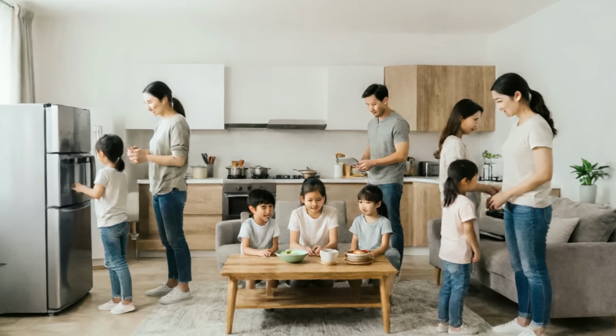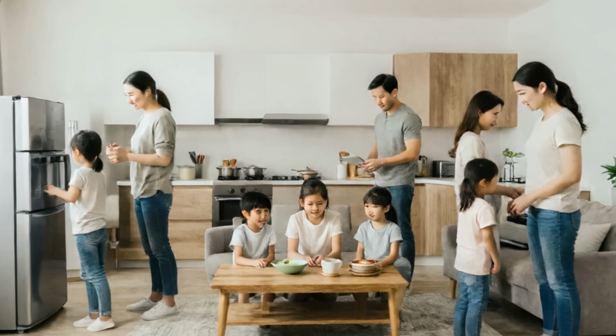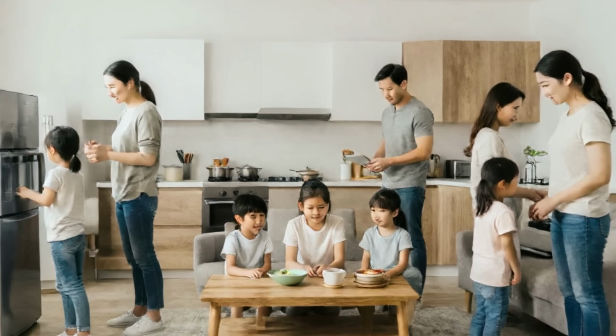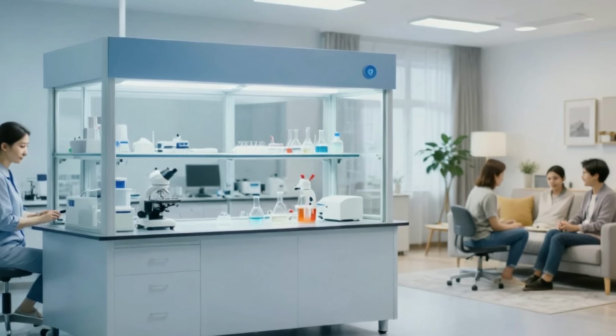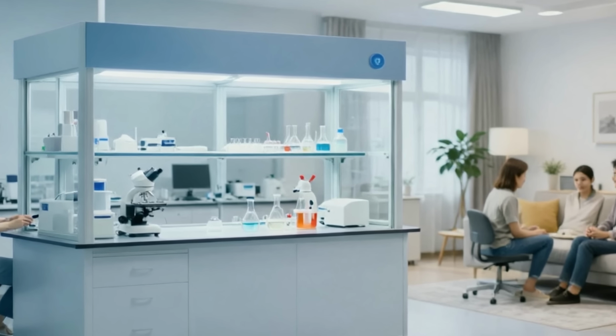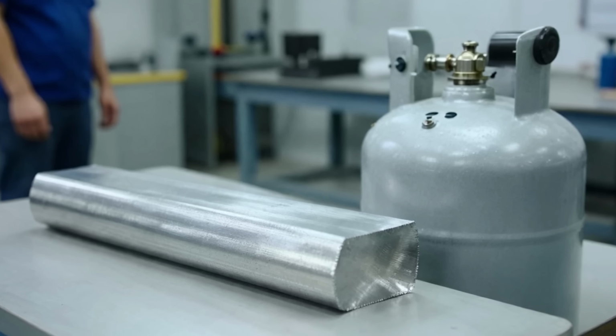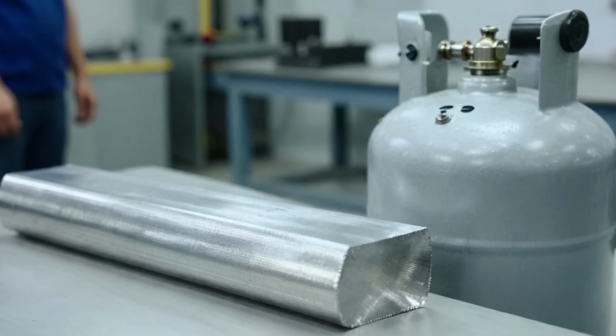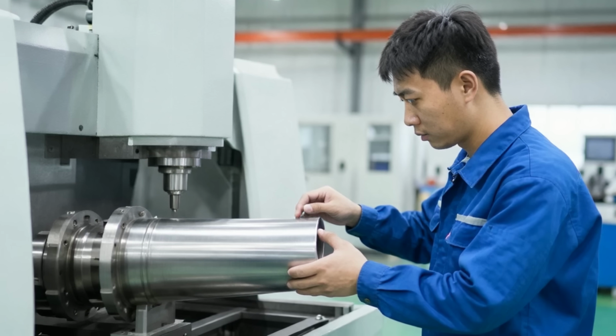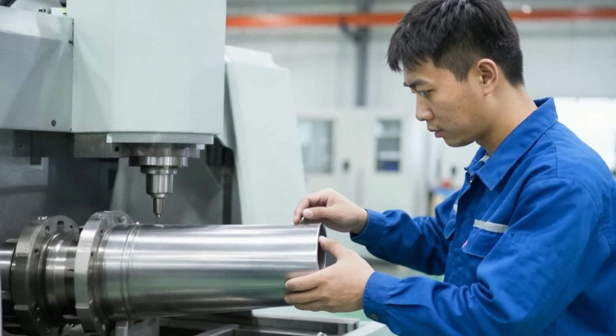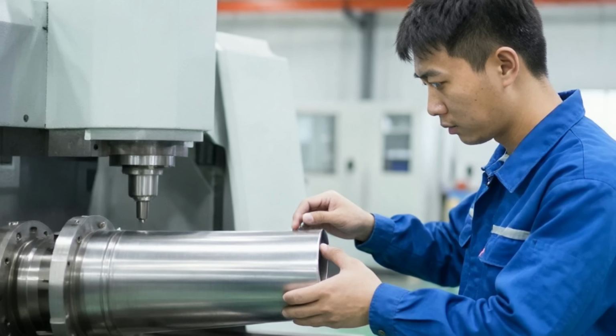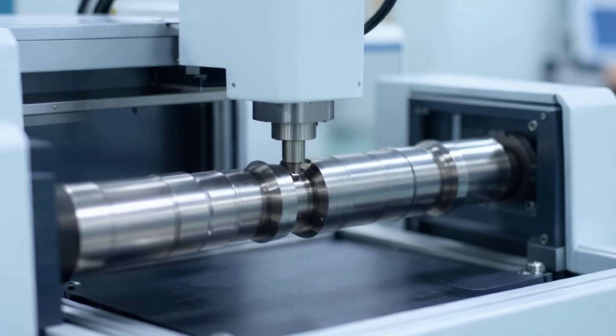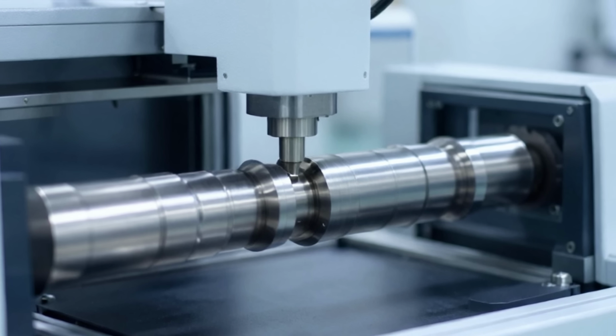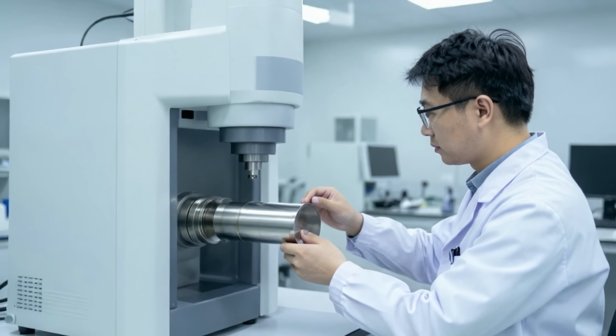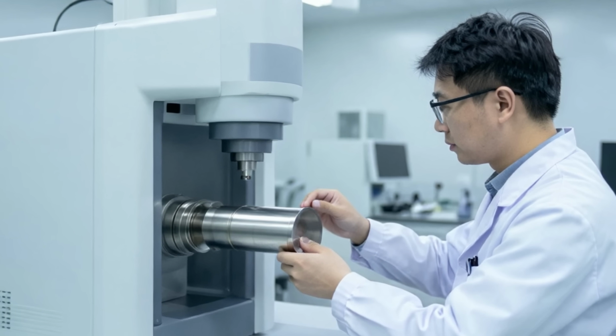Then there's the material cost. Nickel-titanium alloys are significantly more expensive than the HFC gases used in standard air conditioners. The alloy must be manufactured to precise specifications. It has to withstand millions of compression cycles without fatigue cracking. And while the HKS team confirmed through X-ray tomography that their tubes maintained structural integrity under 950 megapascals of stress, long-term durability testing over years of continuous residential use is a different standard entirely.